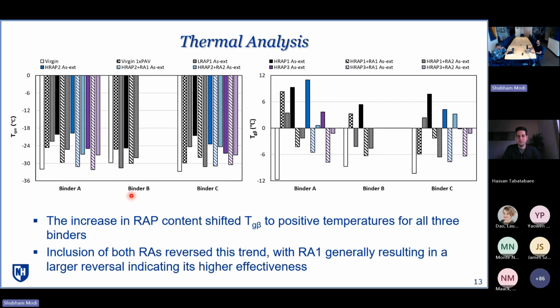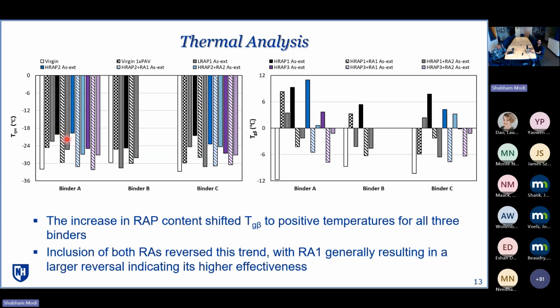And here, as discussed, the Tg alpha parameter and Tg beta parameter are shown in graphical format, and we can see that the inclusion of RAs clearly indicated an improvement in Tg alpha and Tg beta. Especially on the Tg beta side, the inclusion of RAP negatively impacted it, moving it to more positive values, and the RAs reversed this trend and moved it in the more negative direction, which is the desired one. And RA1 is clearly showing better improvement than RA2, meaning that RA1 is potentially more compatible than RA2.